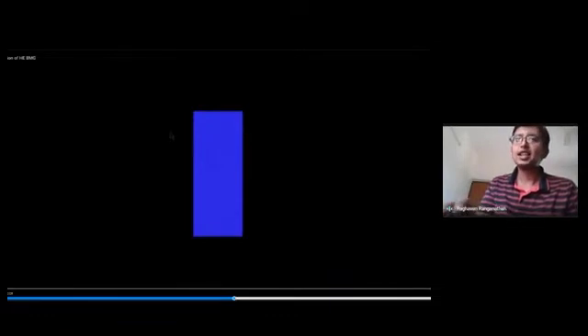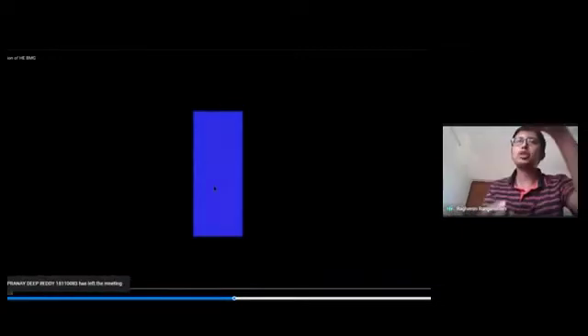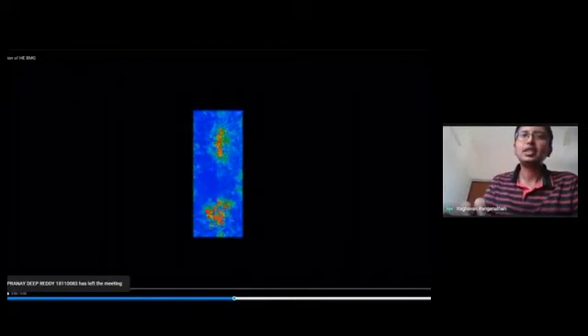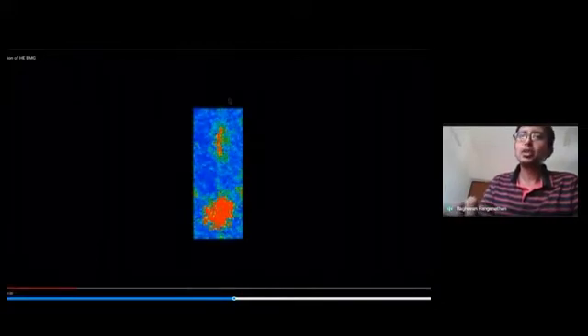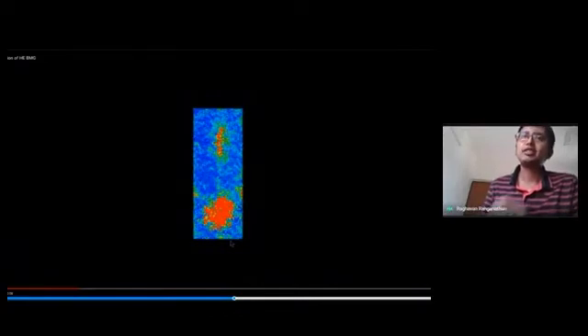Okay? So this is the undeformed structure. And what we're doing is we're applying a tensile force on the top and the bottom. We're basically pulling it along the vertical axis. And what we are showing by color coding is how much strain develops in the material at a very, very local scale. Okay? So all these sizes that you're seeing are of the order of a few nanometers.